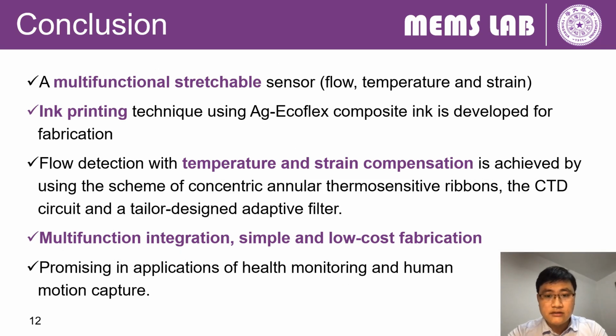In conclusion, we propose a multifunctional stretchable sensor that can detect the flow, temperature, and strain stimuli simultaneously. Low-cost ink printing technique using our homemade silver Ecoflex composite ink is developed to fabricate the sensor. The flow detection with temperature and strain compensation is achieved for the stretchable sensor by using the scheme of concentric annular ribbons, the CTD circuit, and a tailored design adaptive filter.